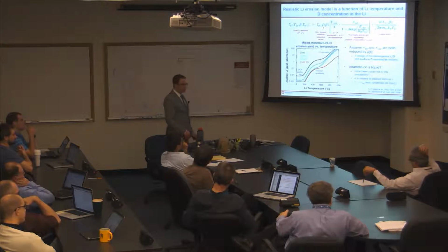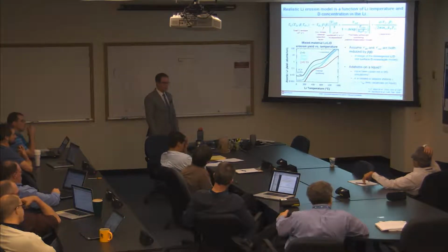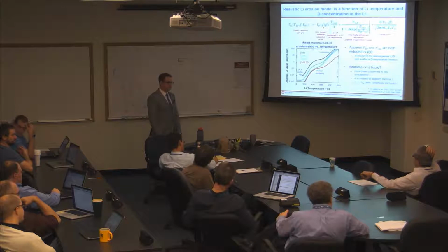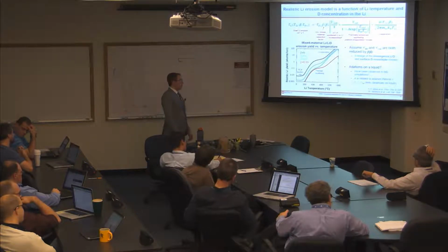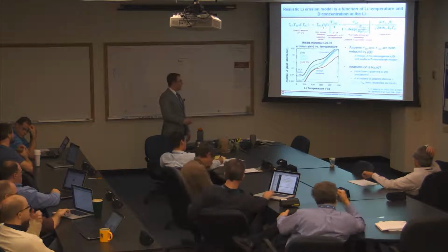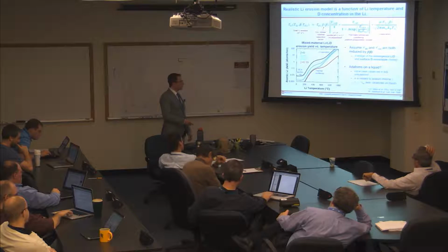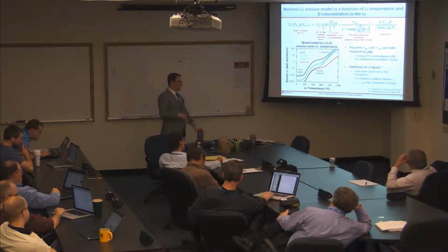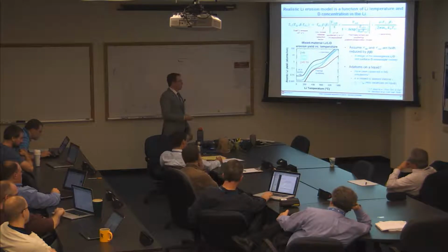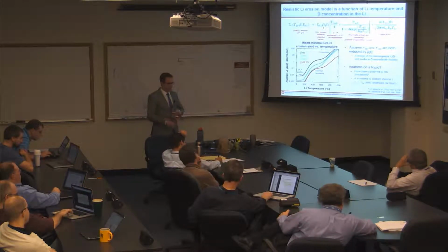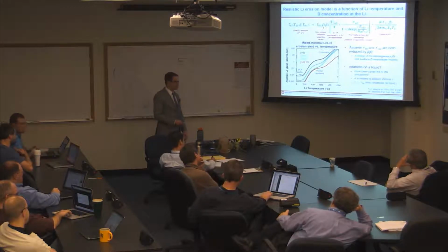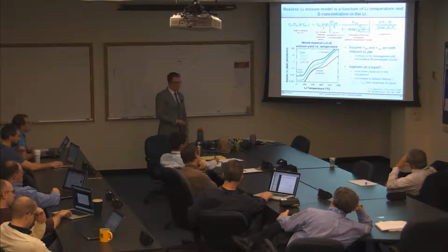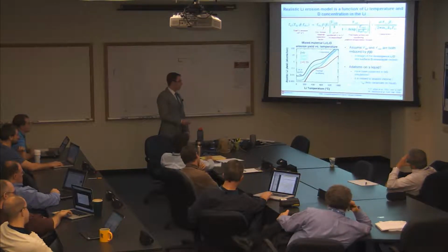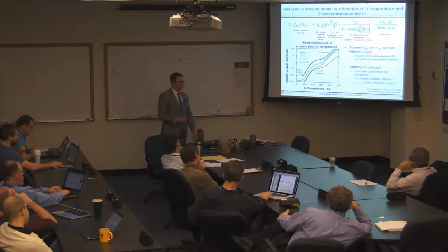Okay, to clarify that, when you say fewer vacancies on liquid, are you saying there's some relationship between vacancies and the process by which you have atoms bound on the surface? Right. I'm not sure if I exactly understand your question, but basically, an add atom is loosely bound. It goes through surface diffusion. And you would imagine, a liquid is something sort of amorphous, so it doesn't really have vacancies per se. So you would expect that it wouldn't really be able to find a vacancy to go into. So you would expect that it would spend a lot more time as an add atom before it finds somewhere to go or it's sublimated off. Whereas for a solid, it can find vacancies.